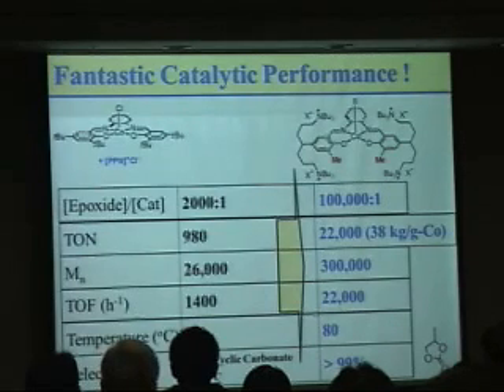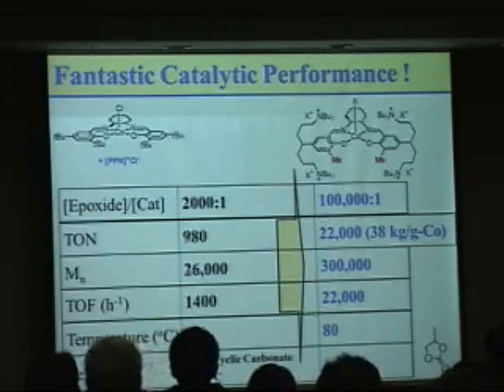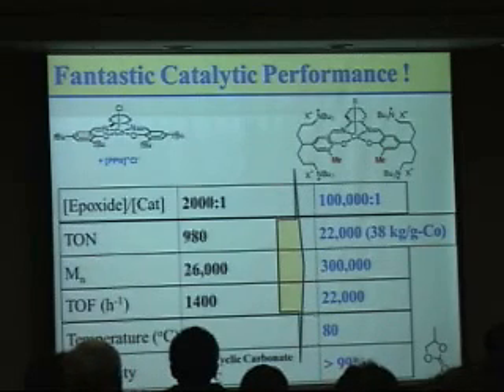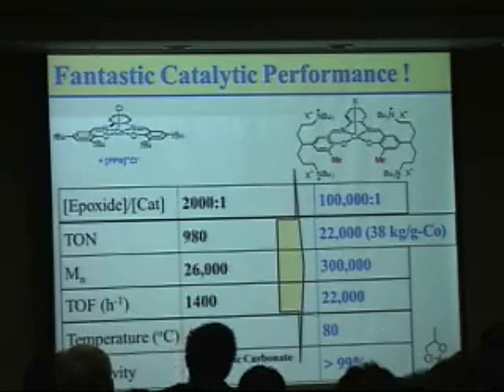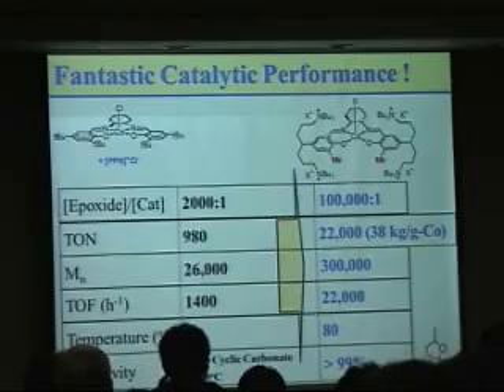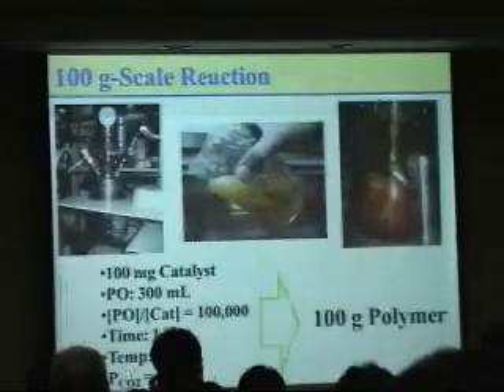At this condition, by getting full conversion, we can get a turnover number of more than 20,000. Due to the high turnover number, high molecular weight polymer is obtained. And interestingly, turnover frequency was also dramatically improved, 15 times. And it works at a high temperature of 80 degrees with very high selectivity.